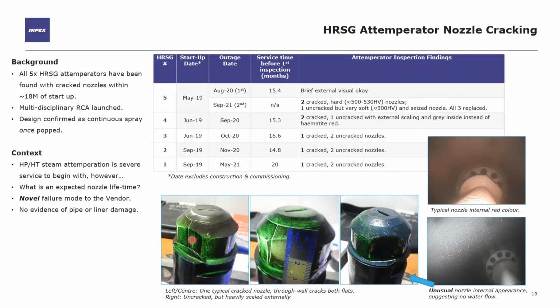Typically, the external cracking shows up through mag particle as cracking through all the flats. Though once or twice we occasionally see these heavily scaled and dirty-looking nozzles, and if you look on the inside of it, you have this metallic gray appearance, which to us is very indicative that this hasn't been firing water, compared with the vast majority of nozzles which have that classic AVT oxide red color. When we first asked the vendor about it, to them this was a novel failure mechanism that they'd never seen before, though fortunately we hadn't seen any pipe or liner damage as of yet.